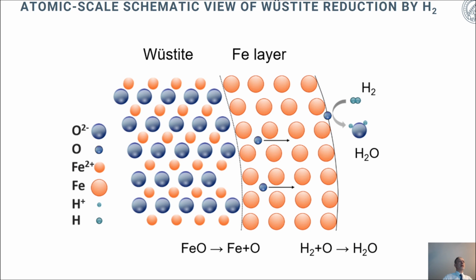The theoretical picture behind this reaction is shown in this diagram. You have here the last stage of the overall reduction sequence, which is the wüstite, the FeO, such as shown here. And as you reduce in the beginning that material through a surface reaction between hydrogen and the oxygen, you form a layer of iron on top of the wüstite. And that means that due to the gradient in the chemical potential, the oxygen must leave the oxide and diffuse outbound towards the free surface or pore or surface of the pellet to react there with hydrogen to form water. And these are the different kinetic steps that have been considered and might act as individual bottleneck reactions for the overall kinetics. And it is a task to identify these bottleneck steps in the overall kinetics and find solutions to make them faster, to make this type of production route viable.